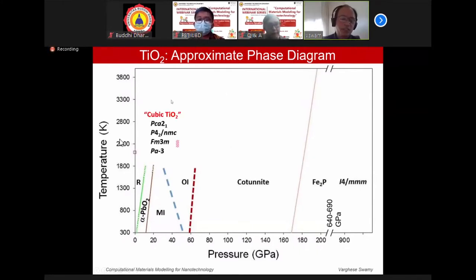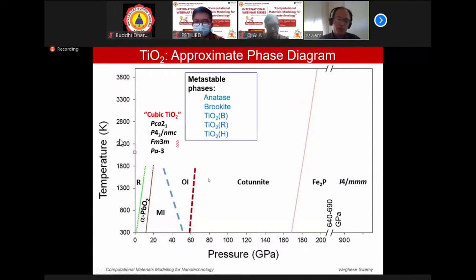So on the missing phase, I was looking for cubic TiO2. Different people have come up with different crystallographic structures for that. Pa3 is the pyrite structure. Fm3m is the fluorite structure. And the other structures are given here. And when we are talking about TiO2 commonly, we are talking about phases like anatase, brookite, et cetera, which are metastable phases, meaning these phases are not thermodynamically stable, but they are stabilized in nature because of kinetic reasons. I'll be talking a bit about anatase later.